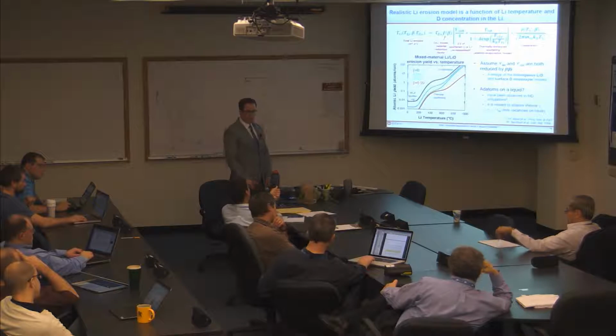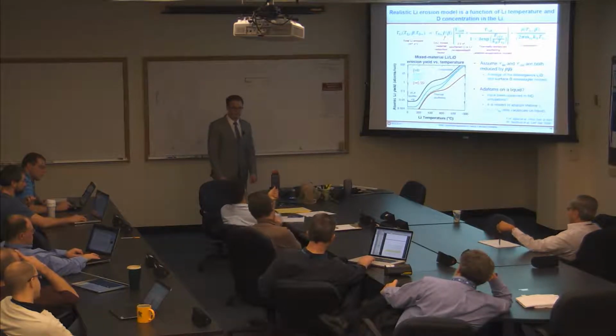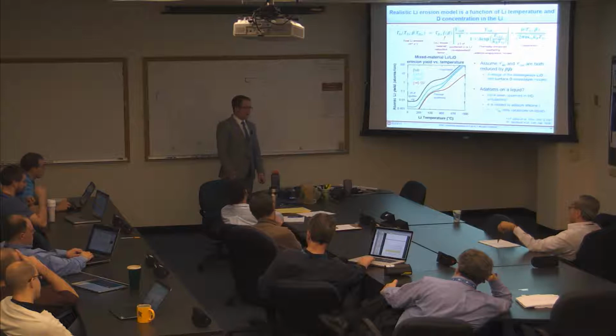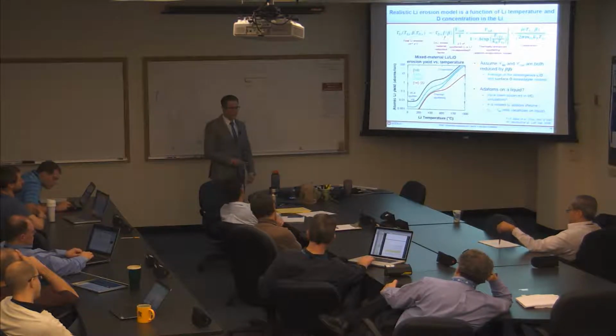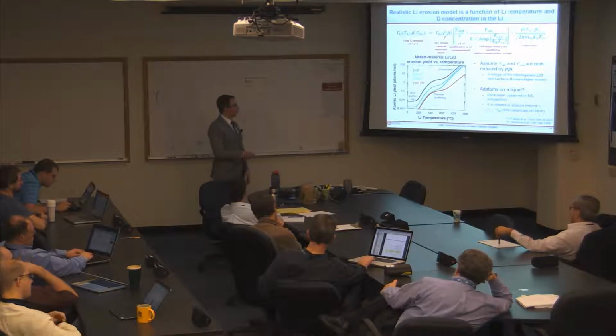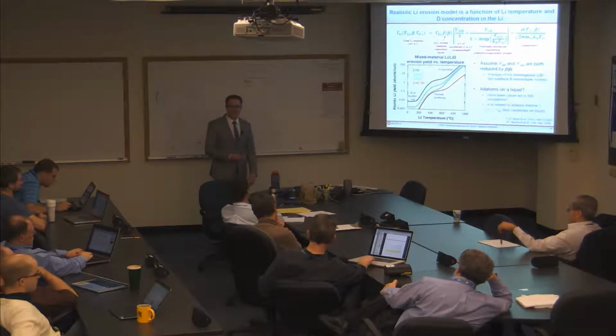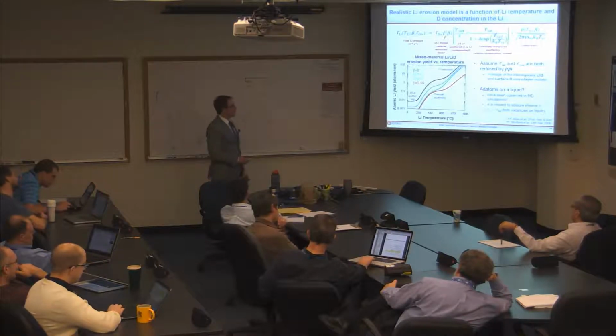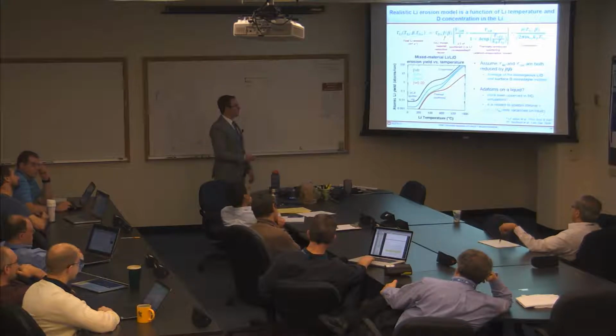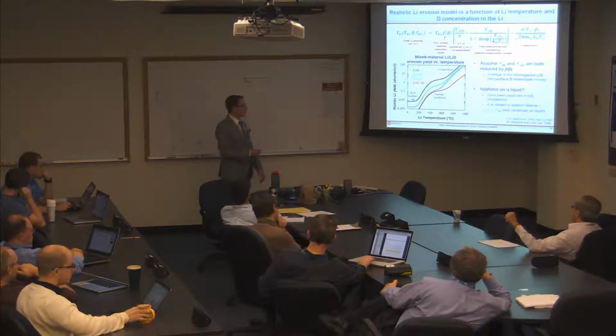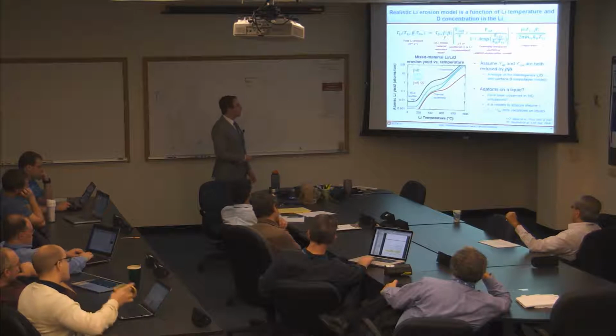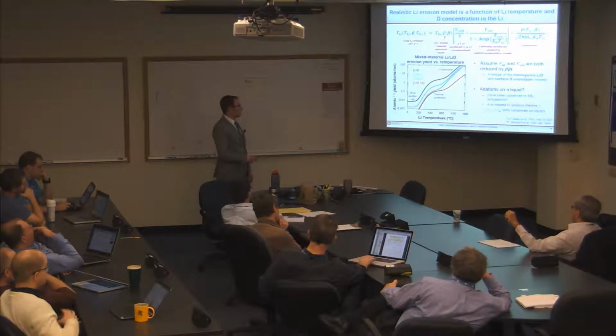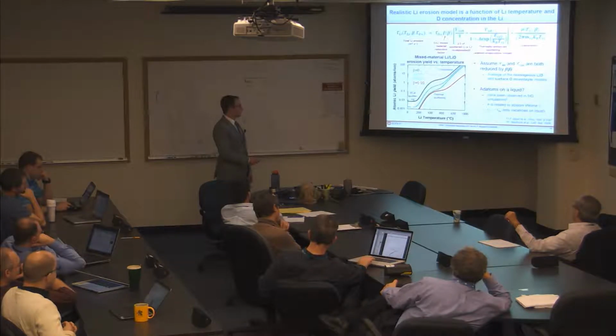Tyler, there was a competing thermal enhanced sputtering model that you thought about, the thermal spike one. Do you want to comment on how that one differs from the adatom evaporation model? Sure, I can. I didn't really talk about it because this model ended up fitting the data a lot better, just in terms of making it a linear story. But basically, the thermal spike model doesn't have this one term right here. And so it basically says that erosion, or temperature-dependent sputtering, can increase indefinitely rather than plateauing at some value. If you plotted the thermal spike model, it would continually, exponentially increase from 200 up to infinite temperature rather than having this plateau.